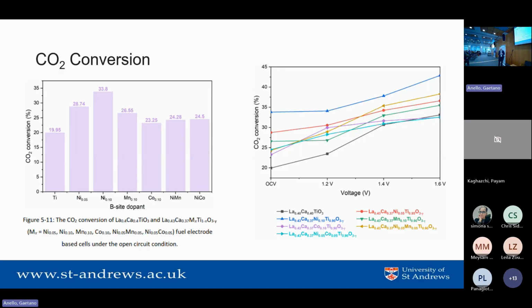And people will often say you need transition metals to be reduced, but actually, if you can get enough oxygen vacancies and enough titanium 3+, the strontium titanate works perfectly well and better than the cobalt in these cases.